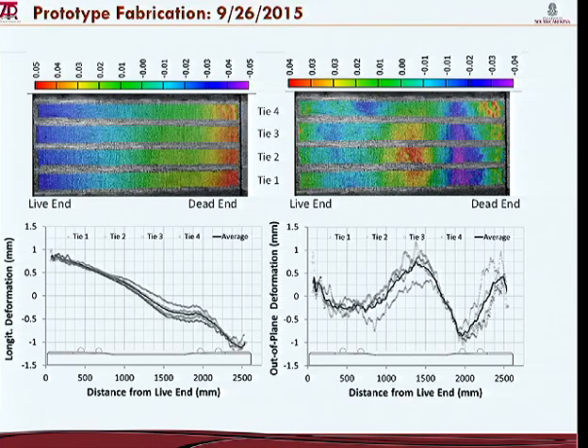Then we looked at the out-of-plane deformation. So the deformation that is shown here is the actual lift of the surface of the tie in the vertical direction. And we noticed that in this lift, there was something that was holding the tie down. What you would normally expect if you compress the tie and you have some eccentricity in it, you will see a uniform curvature. But instead of seeing this, we picked up some catching there.